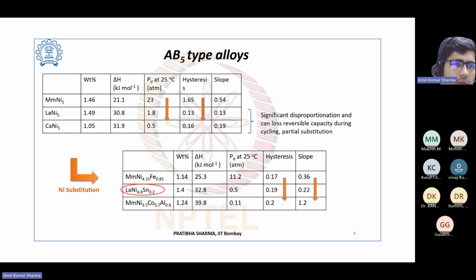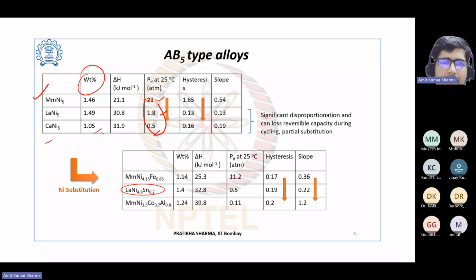If we compare MmNi5, LaNi5, CaNi5, you can see the weight% 1.46, 1.49, 1.05. The desorption pressure at 25 degrees is 23 atmosphere, 1.8 and 0.5. See the difference, there's a huge difference. So we can change this property. Where we have a very high pressure application, maybe we can use this alloy, and if you want a low pressure application, we can use that alloy. Between these two, the weight% difference is not that much, but if you see the desorption pressure, it's totally different: for the first one it's 23 atmosphere, and for this it's only 1.8 atmosphere.